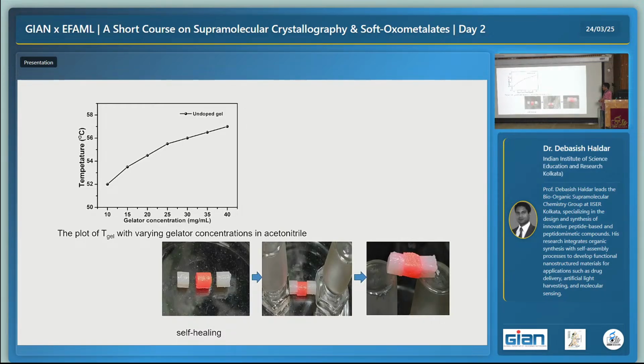Also we have studied the melting point of the gel, and what we have seen is that with increasing gelator concentration, so if the gel is a very concentrated one, the melting point is going to increase. And the gel has very good self-healing property. That means if we cut the gel in pieces and put them together again, they will self-heal, they will make a single bar or single fiber from the gel.